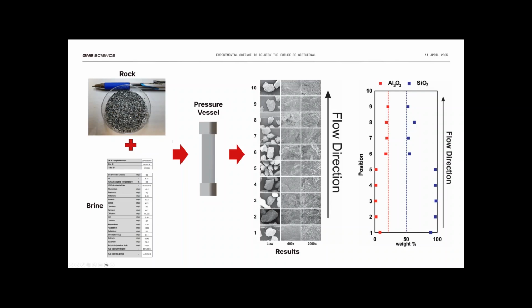So we take the rock and the brine, we put the rock in the pressure vessel, and we flow the brine through the preheater and then the pressure vessel, the reactor, which contains the rock. And that can be at the reinjection temperature, which is typically 80 degrees to 150 degrees. So this is typically done over 28 days. We keep a standard protocol so that we can compare experiments. So done over 28 days at whatever reinjection temperature at a flow rate of 5 mL per hour, which gives us enough sample every day to do our chemical analyses.